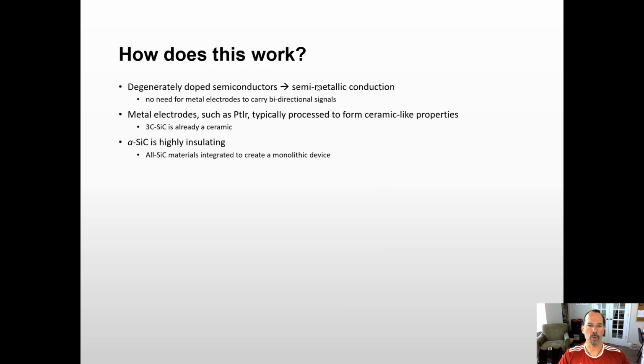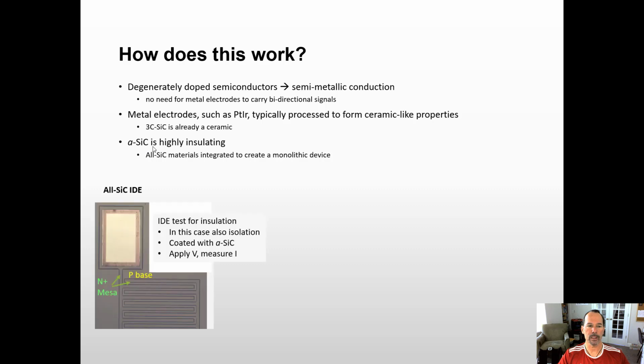So again, how does this work? I just mentioned the semi-metallic conduction of the heavily doped N plus layer, and then we can think about how a lot of devices use, for example, platinum iridium sputtered or coated on the recording tip to give it ceramic-like properties. Well, cubic silicon carbide is already a ceramic, even though it's a semiconductor. So we don't need to add an extra coating that can over time delaminate and fail. And again, we have this amorphous silicon carbide that's highly insulating.